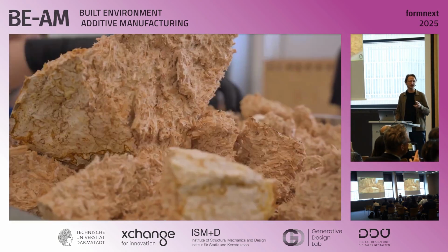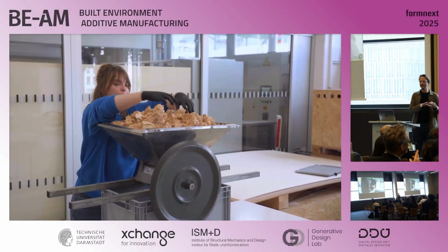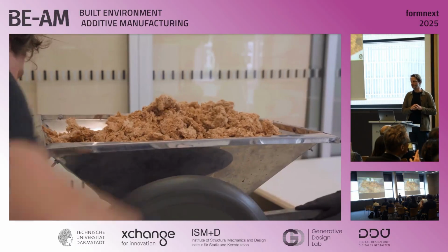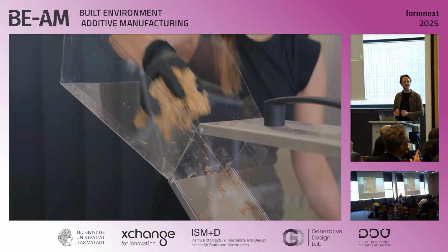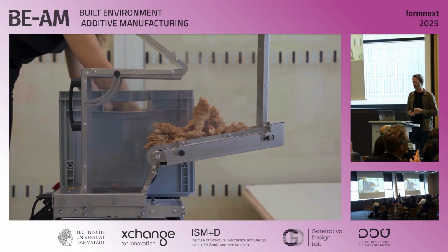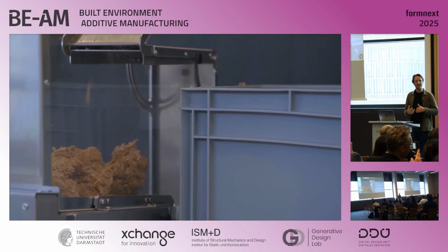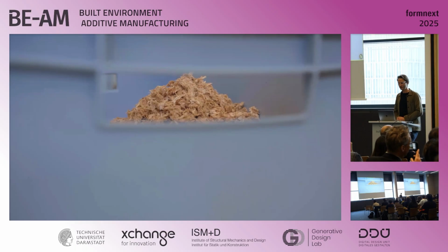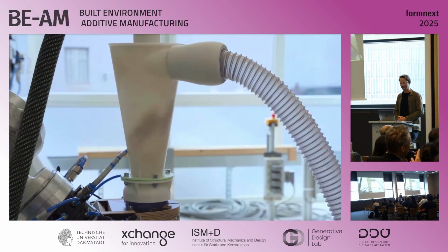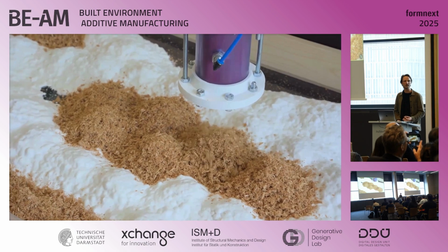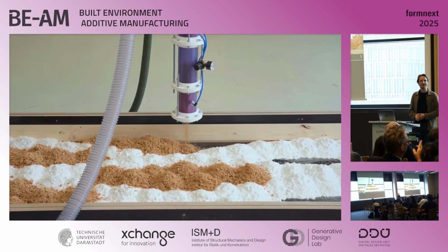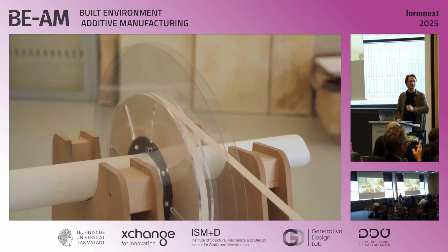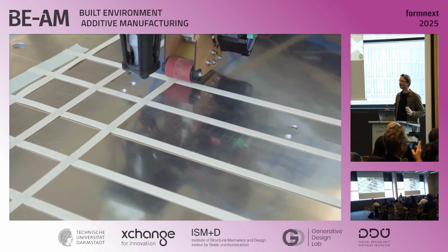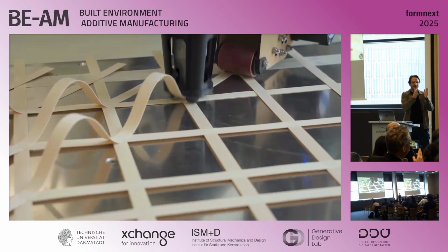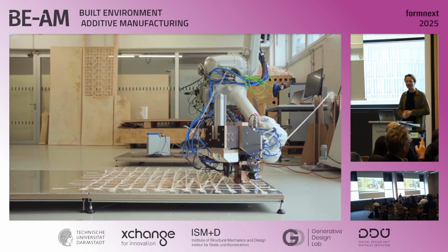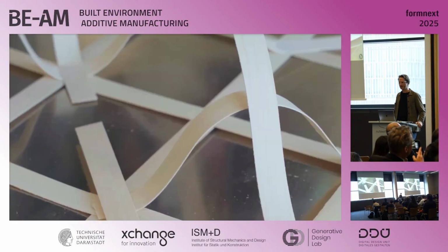You also see it's a process where these substrates require different growing times. First, you have the sawdust, which is more dense and needs longer for the mycelium to grow through it. So it's deposited first, we let it grow, and then the second material comes in, which is the hemp. There you can see a bit how this tool works. At the moment it's very coarse, but it's also a coarse material. We don't necessarily need millimeter precision, and we want to make large components. We're not looking at a 20 centimeter component, but a 2.5 meter component.